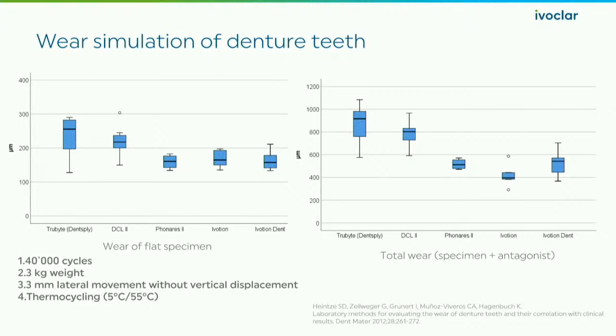We're trying to figure out and scratch our head, why are we seeing this? Because DCL's a harder tooth. You know, why is it wearing? And why is the Ivotion milled tooth and the Ivotion monolithic tooth not wearing as much? And we dug a little deeper and compared it to the intraoral study, and it showed a consistency with wear, what's happening in the mouth, what's happening in the lab. The red line shows a pretty straight, consistent measurement going on. They had actually a little more wear when it got in the mouth.